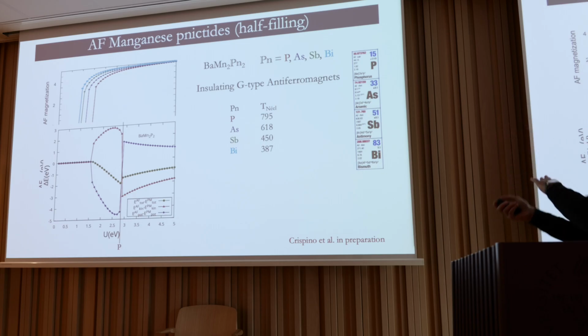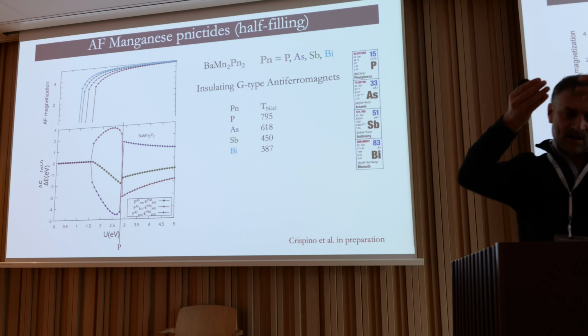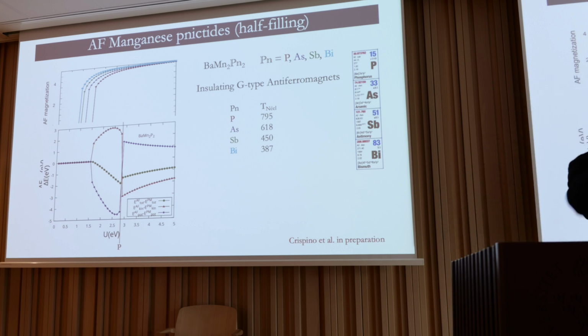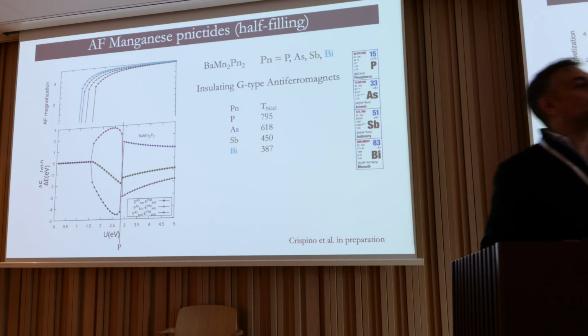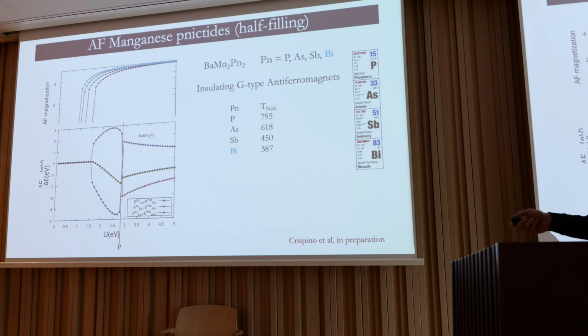Weak coupling is the Slater antiferromagnet, which is stabilized by the potential energy, which is negative. The difference between paramagnetic and antiferromagnetic potential energy is negative, while the kinetic energy has a positive difference. Then you change completely regime here, and you go to a strong coupling regime, which is stabilized by the kinetic energy gain, typical of a local-moment antiferromagnetic phase.